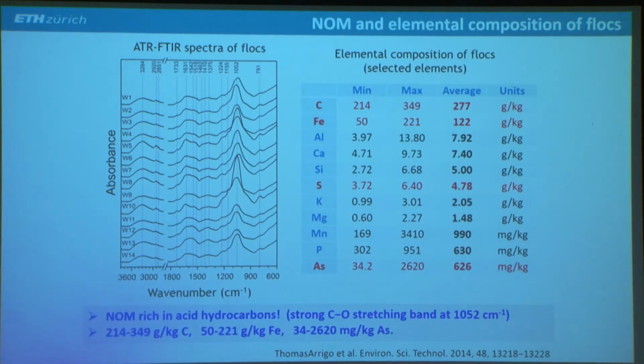And of course, we had to characterize them as well and look at the speciation of arsenic, iron, and sulfur in these flocks. And the first slide I'm showing is some ATR-FTIR, so infrared absorption spectra of the flocks. And the most prominent feature here was this very strong absorption band around 1052 per centimeter wavenumber, which is a C-O stretching band, which is indicative of acid carbohydrates, and it's very typical for EPS-like organic matter that is, for example, excreted by algae or microorganisms. But there's also some humified organic matter in these flocks.